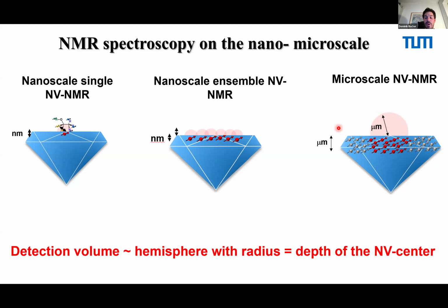And what is the advantage? You might see it as only a disadvantage to go from a single NV to an ensemble because, of course, you lose this very beautiful nanoscale spatial resolution. That's true, but at the same time you win sensitivity because you average over many NV centers, and this gives you higher sensitivity, but also more robustness because you have a much stronger fluorescence, which is good in particular if you do chemistry on the surface.